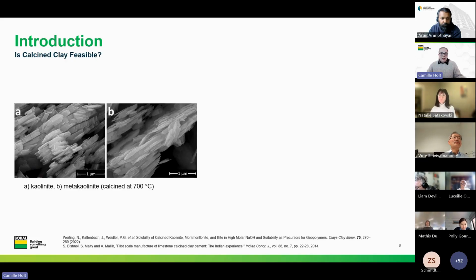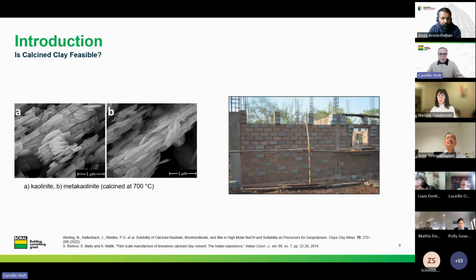The production of clay as an SCM has already been trialled overseas, with pilot scale trials having been conducted in India and Cuba as part of research into the limestone calcined clay cement, or LC3, binder system, which has proved the feasibility of clays as a partial cement replacement. Australian standards are also now beginning to include calcined clay through AS 3582.4, the manufactured pozzolan standard.